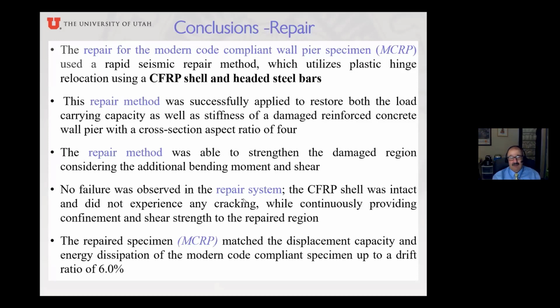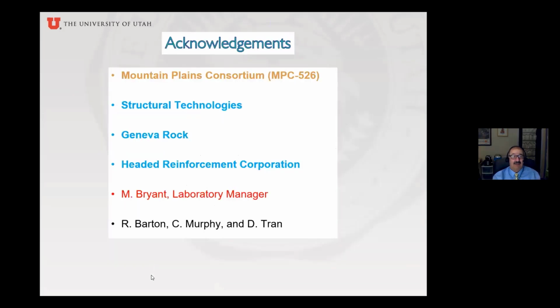No failure was observed in the repair region of the system, and the shell was intact. It did not experience any cracking, and it continuously provided confinement and shear strength to the repair. So the repair specimen matched the displacement capacity and energy dissipation of the original modern code compliant specimen up to a drift ratio of 6%, and we didn't want to go above that.